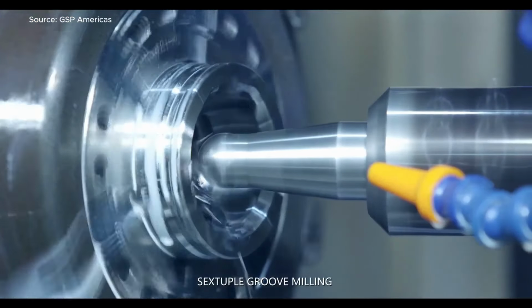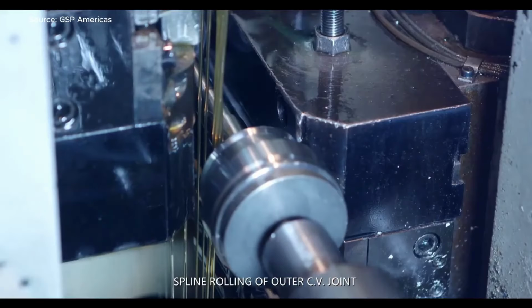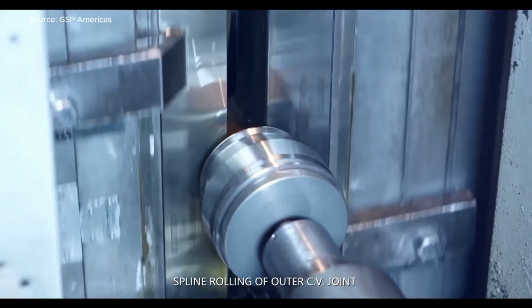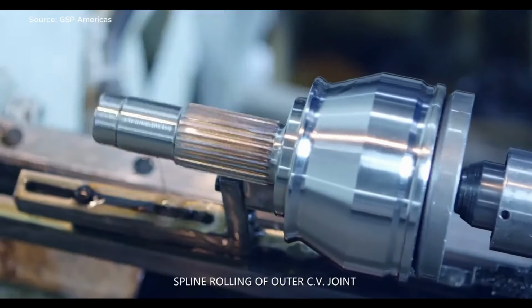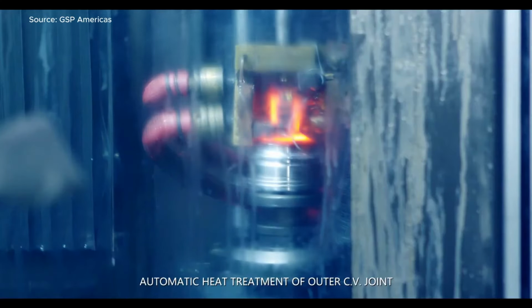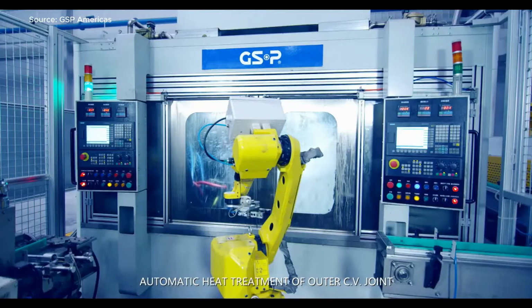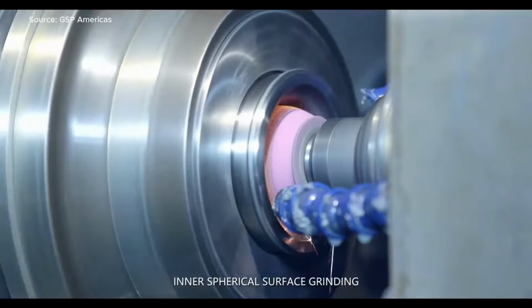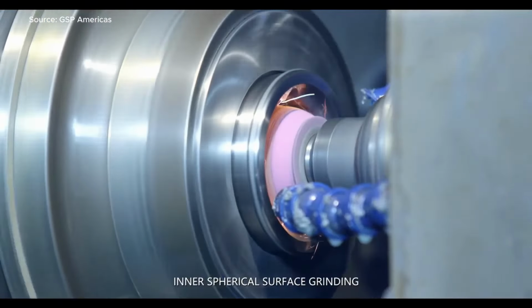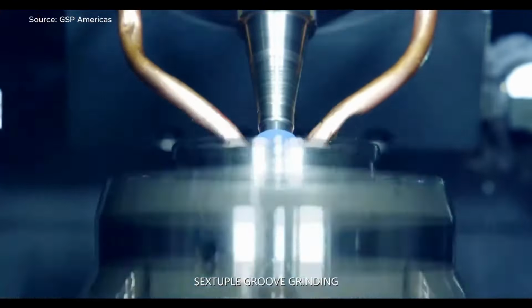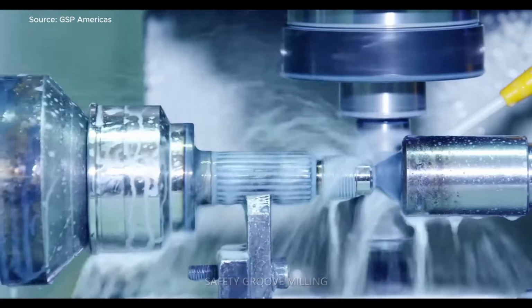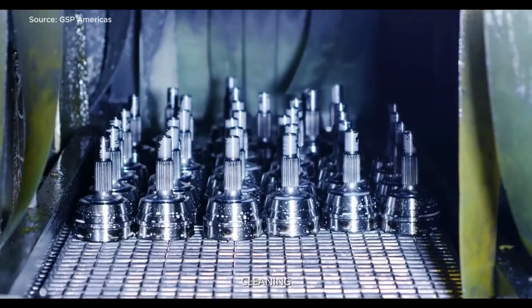The production process of the GSP drive shaft involves several key steps, each with precise specifications. First, high-quality alloy steel, such as C45 or 20CrMnTi, is selected. The material undergoes cutting to lengths ranging from 1,000 mm to 1,500 mm, followed by CNC machining with a tolerance of plus or minus 0.05 mm to shape components like grooves and holes.